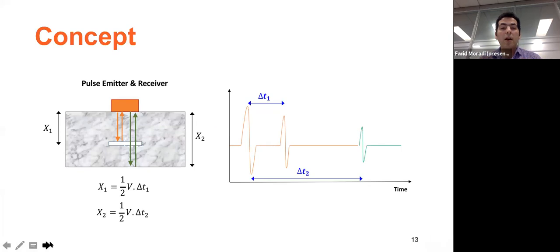The other category for pile condition assessment is pulse echo. The concept is easy: you have a source at the surface that sends signals. Signals reflect off defects and boundaries. The first peak in the signal is emitted by the hammer impact, the second is the reflection from a defect in the midline, and the last is the reflection from the back end. Based on a simple calculation, we can find the location of defects or understand the thickness and boundaries of the material.